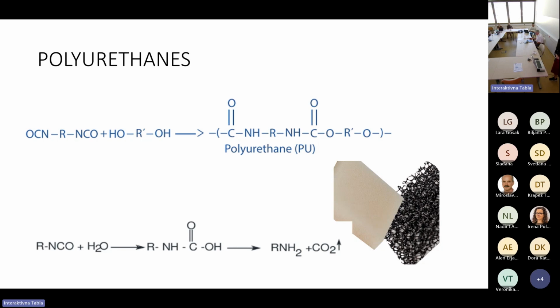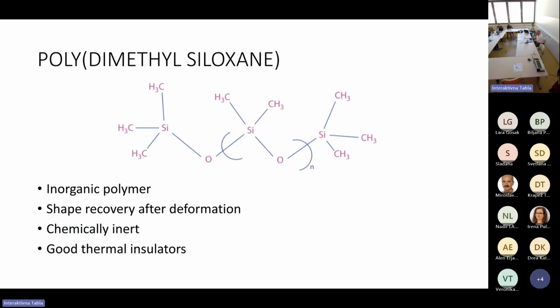And how is this porous structure produced? Of course, it can be done in different ways, but one of them is to add water to the reaction mixture. Water reacts with isocyanate and produces carbamic acid, and this carbamic acid is not stable and decomposes to amine and carbon dioxide. Because this reaction of polyol and isocyanate is rather fast, this carbon dioxide remains trapped in the structure. So that's about polyurethanes.